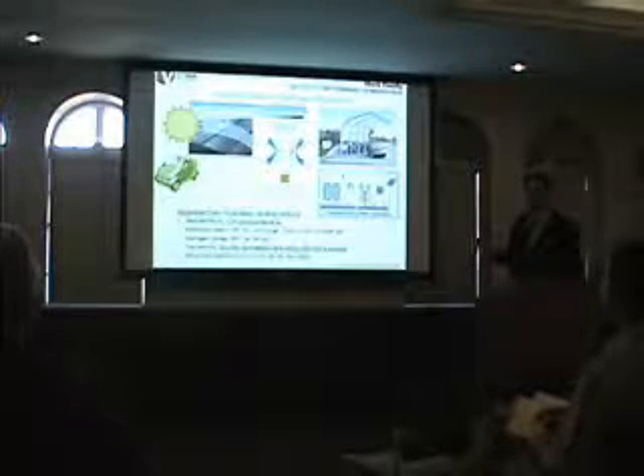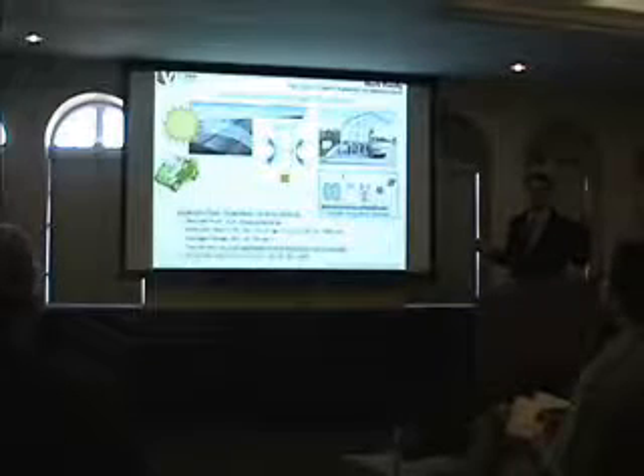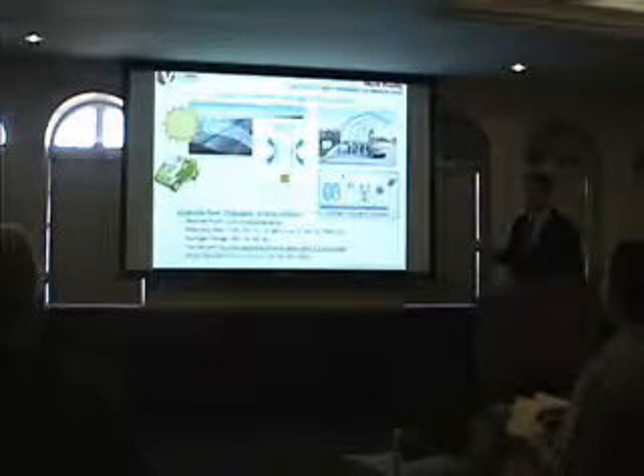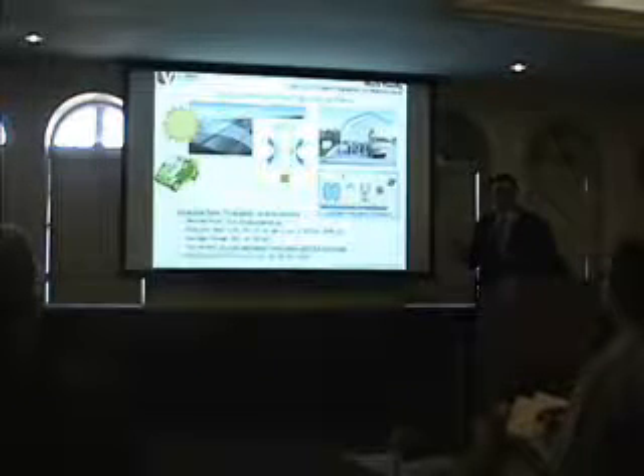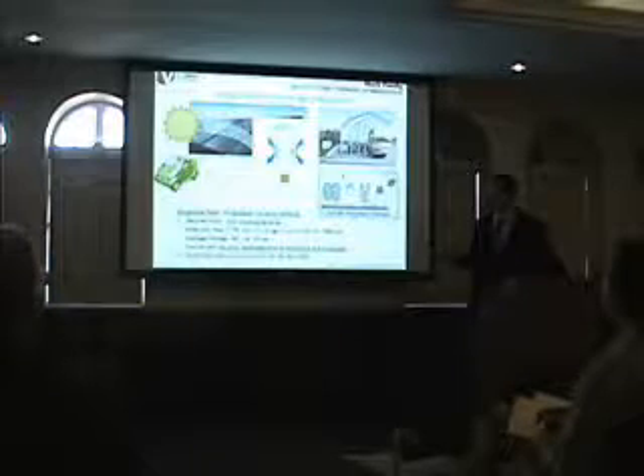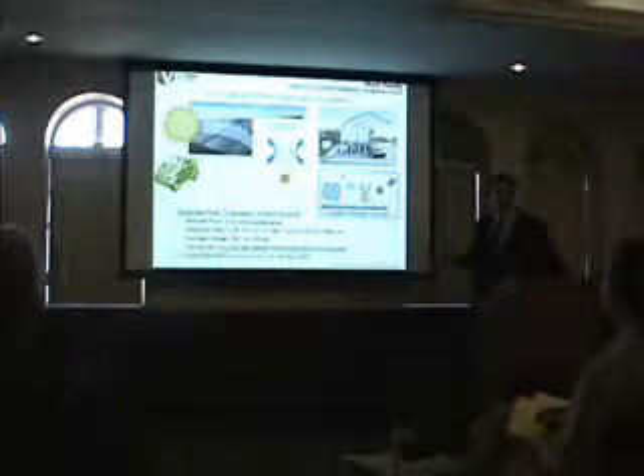You essentially have your solar panel, your power converter, which powers your electrolyzer, which makes your hydrogen and oxygen. Oxygen you just dump overboard, hydrogen is what you want, and then you compress that hydrogen into some hydrogen storage tanks. Now the specifics on this plant are that it takes around 8 kilowatts photovoltaic energy, and it produces around 6,000 liters of hydrogen per year. So that's basically through a year, and it does this at 5,000 psi.